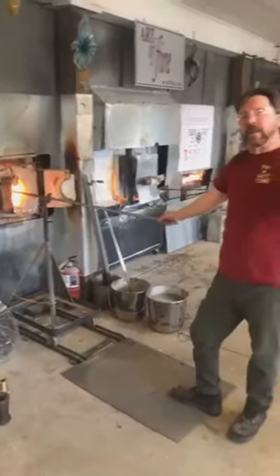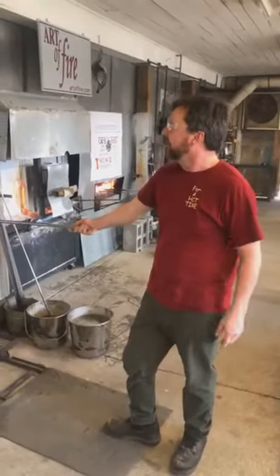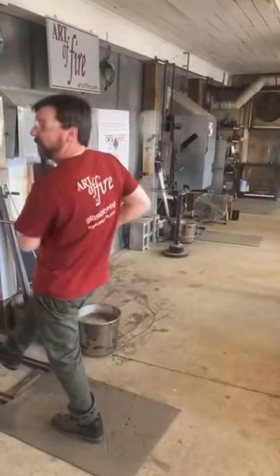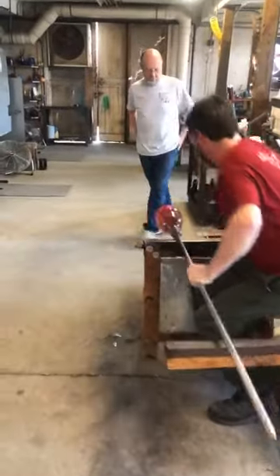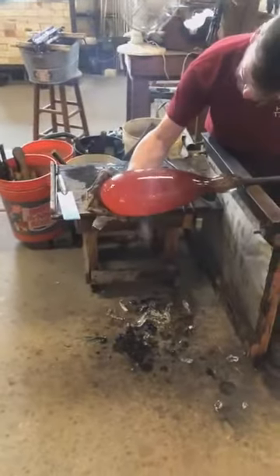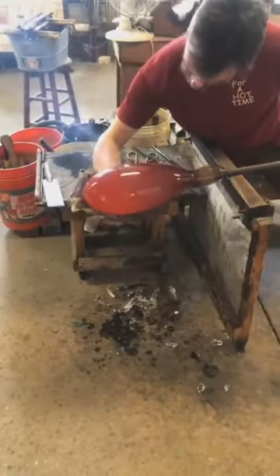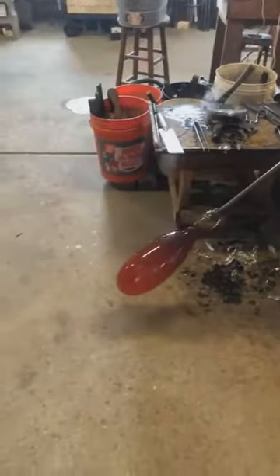And there he goes. Some of the colors are stiffer, some of the colors are softer. And that's part of the impact on this balance, is that the blues and greens and purples want to flow. The yellow, orange, and red are tight, and they're kind of in a little bit of a battle for motion and energy. So it changes the complexion of the piece a little bit. There you go, and that's a perfect explanation. Lots of you have asked before how much color choice affects the working of a piece or its design, and that's a perfect answer right there. If some little parts of this are moving more than others, we've got to accommodate them, but we've got to get the ones that don't want to heat up to temperature. So it's a constant balancing act.